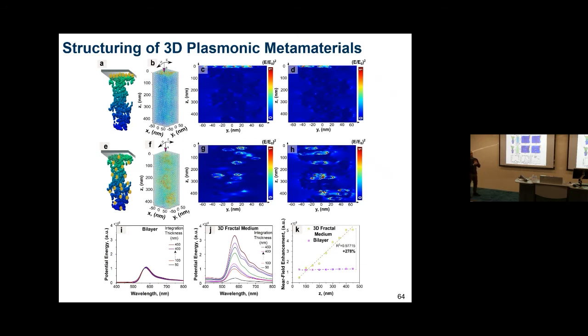Again, we try to simulate what's happening. If you compare the fractal structure with the gold at the bottom versus the fractal with the gold distributed, you can see we have much more hotspots distributed in the volume. We believe these hotspots, because they're also places where the gas can condense since they are porous, increase the response to the gas.